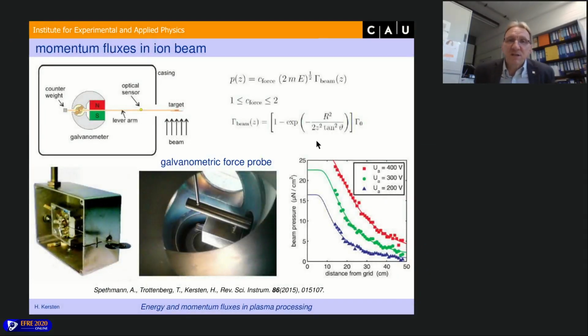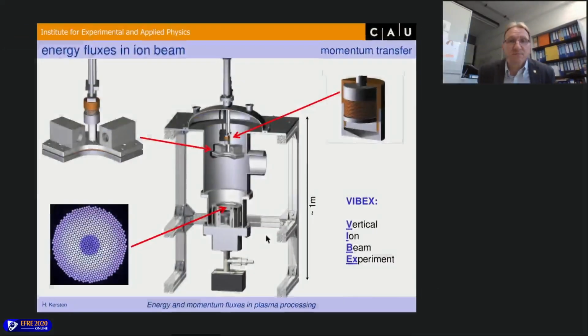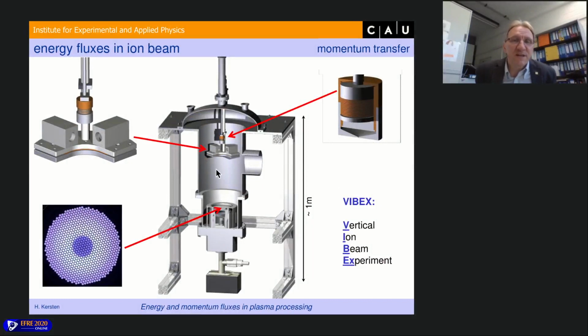And so this brings me now to the other topic. We thought, can we measure not only the energy influx, but also the momentum flux? And if we put such a cantilever target in the ion beam, then we also measured a force by this cantilever, and this force has the same profile as the energy flux. And of course, this force, or the momentum transfer, is generated by ions and neutrals, and the fast recharged neutrals. That we could also see in a very nice experiment.